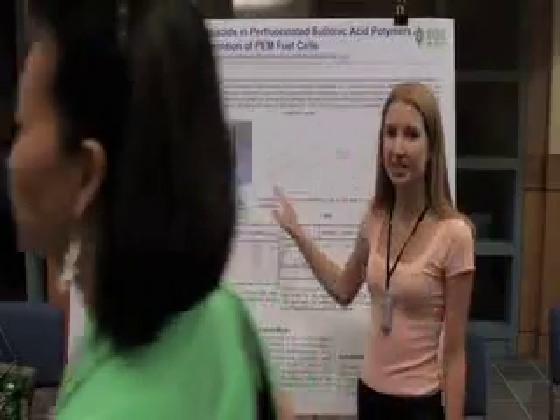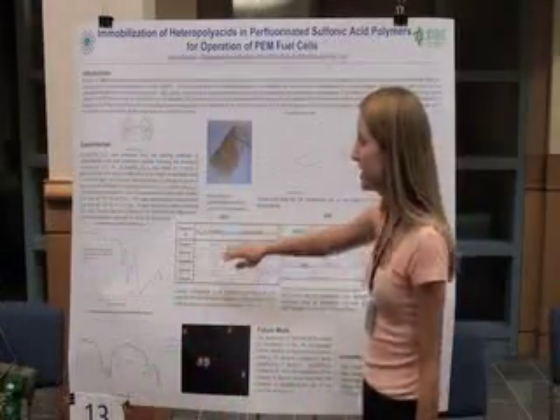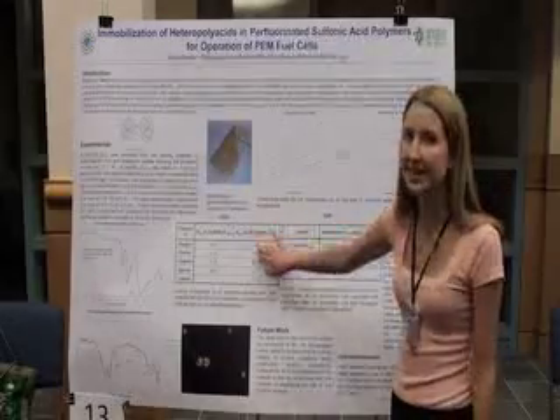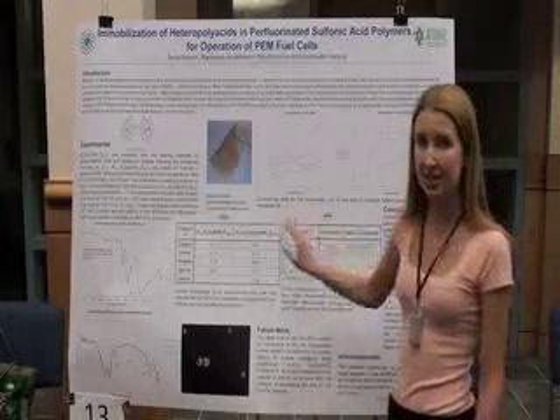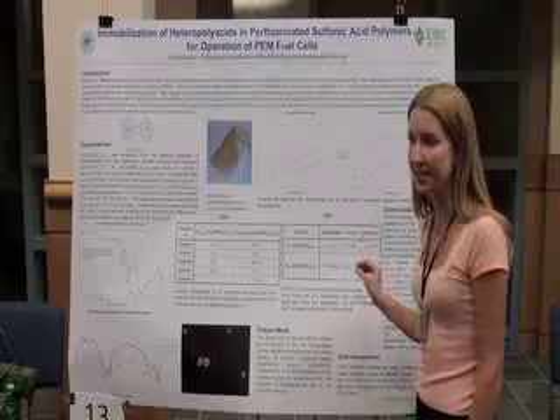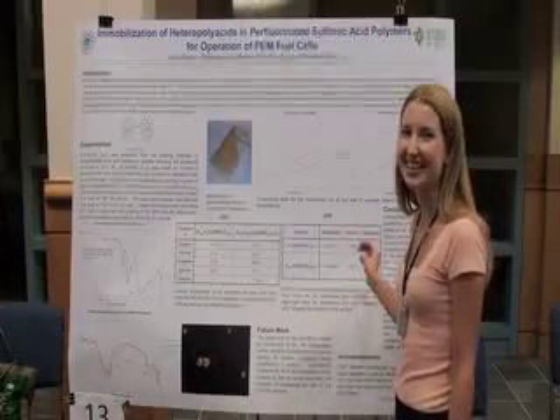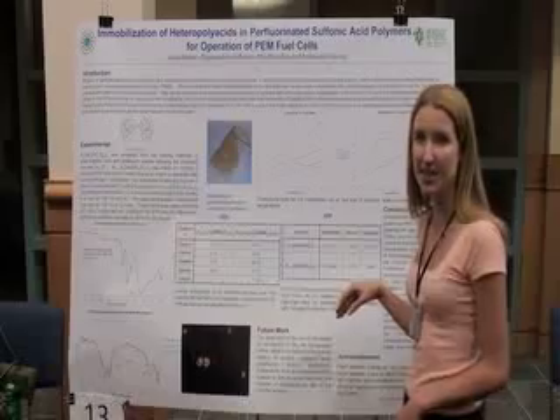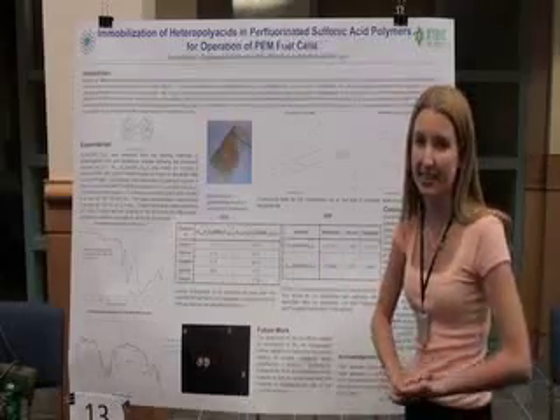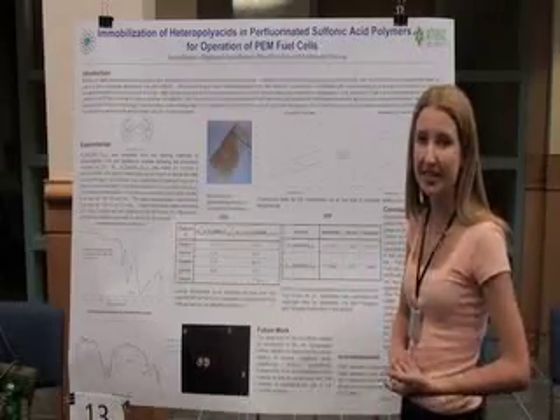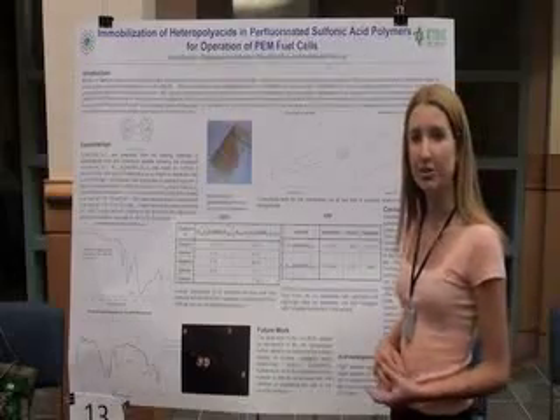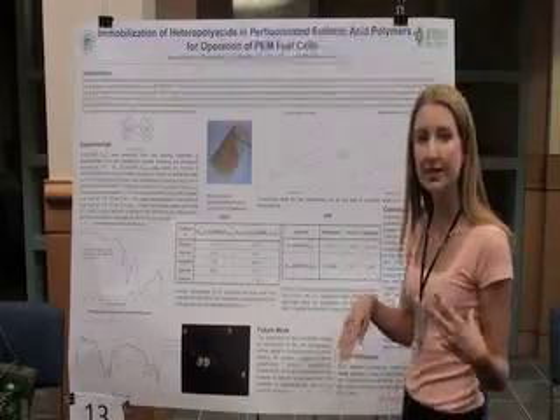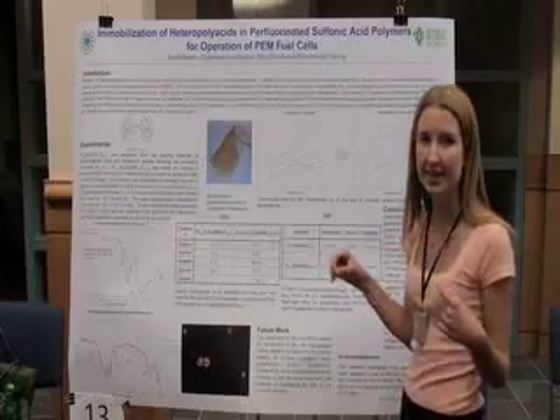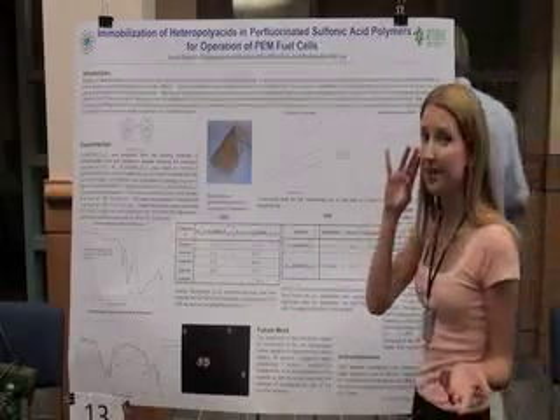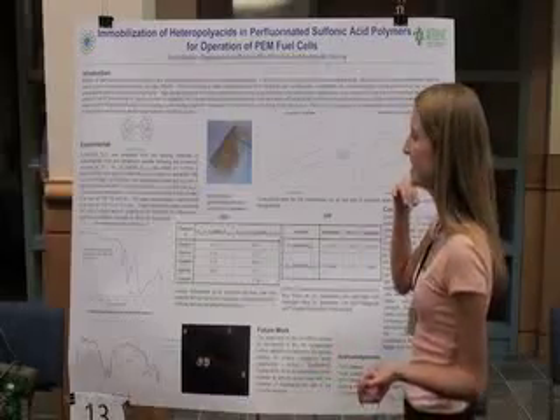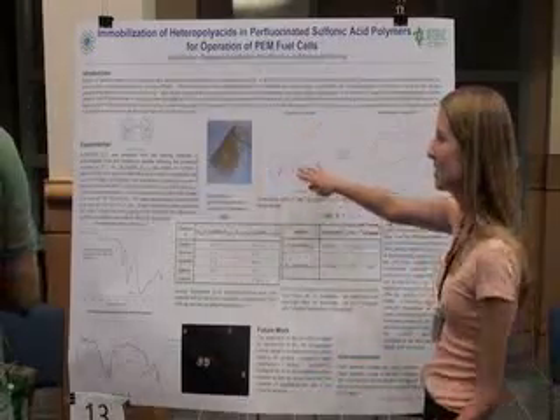I did a simple exchange to do that, and then I did characterization tests using EDX, XRF, and I just did XRD to make sure that cesium was actually in the system. And then I went ahead and did a leaching test to make sure that we're not losing the heteropolyacid. And the results were very promising. It looks like the material is actually more hygroscopic, so it's absorbing water, and even if it's left in a vacuum overnight, it won't release the mass.